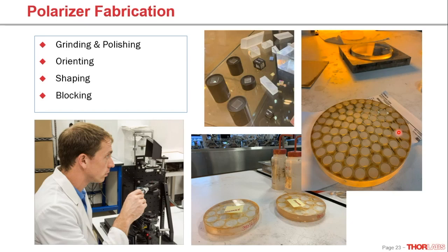With this calcite and that large delta n, for example, if we take it back to the example of the Glan-Taylors that experience that total internal reflection to split those rays, that larger delta n gives us a lot more wiggle room and ultimately a larger angle of incidence to work with on that incoming light, as well as a wider range of wavelengths that can be accepted into those parts.